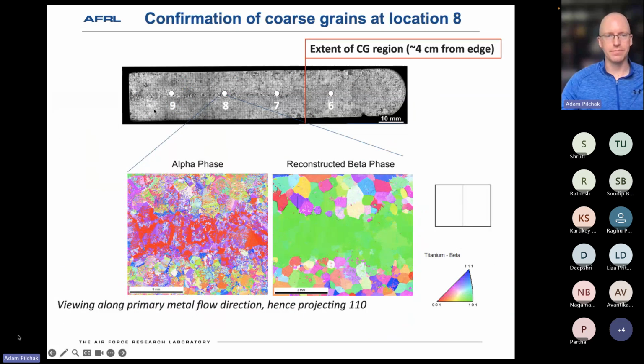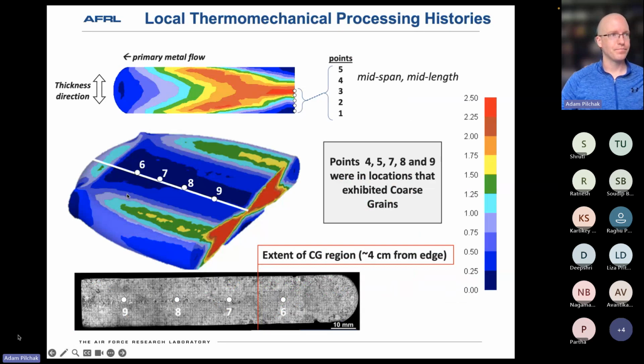All right, this is where I think it gets the most interesting. Here we took an axial section, so the original bar axis is horizontal in this image, and we wanted to see to what extent the abnormal grains went along that direction. We did these massive optical maps and found that until you got about 4 centimeters away from the very edge of the original bar, you saw these abnormal grains. Here are the reconstructions again, and that drove us to choose a number of points.